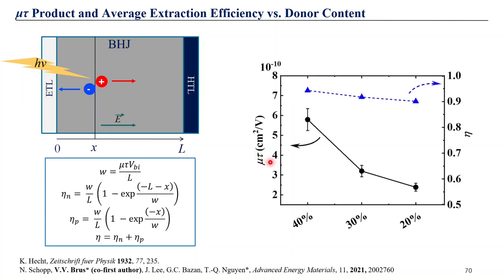When we analyzed the mobility-lifetime product as a function of donor concentration, we see that with dilution of donor, this mu tau product drops. This is expected, because we mentioned the morphological issue, the interpenetrated donor network, so both mobility and recombination lifetime drop, in particular because of increased bulk trap concentration due to morphological traps. However, due to systematic decrease of the thickness of the active layer, we managed to achieve average extraction probability above 90%, which is quite good for all devices. So they definitely do not suffer from poor charge extraction.